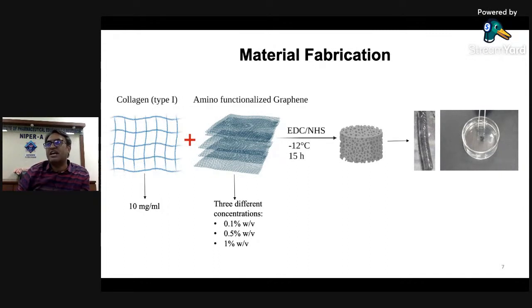When you synthesize the cryogel or hydrogel at sub-zero temperature, these hydrogels are mostly synthesized in water as a solvent. So at sub-zero temperature, the water freezes. When the water freezes, the local concentration of the polymer becomes so high that in small regions, it never freezes, and that is a colligative property, meaning that as you increase the concentration of the solute, there is a depression in the freezing point.